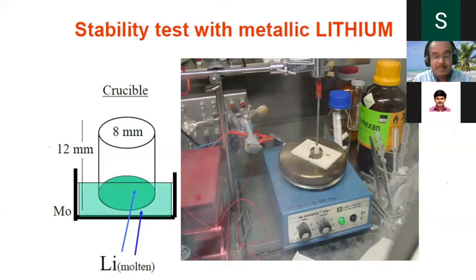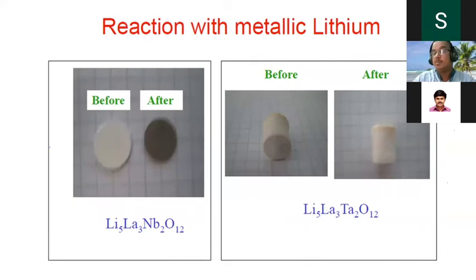And when I published this, there were a lot of questions, because in the garnet case, people want to replace the niobium by tantalum, yet the stability is still poor. But this is the niobium, completely black. It reacts very easily. But this tantalum system is quite interesting, it doesn't react. There were a lot of question marks in those days from the French group, because in the garnet structure tantalum was thought not to be stable. So that's the concept behind what you call thermodynamic stability and kinetic stability.